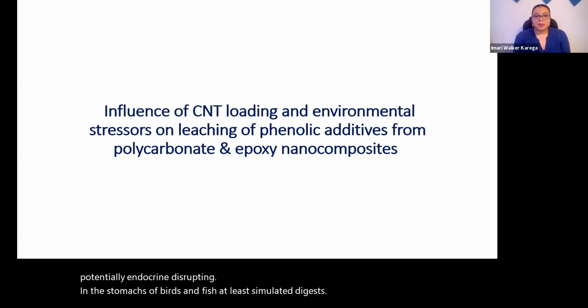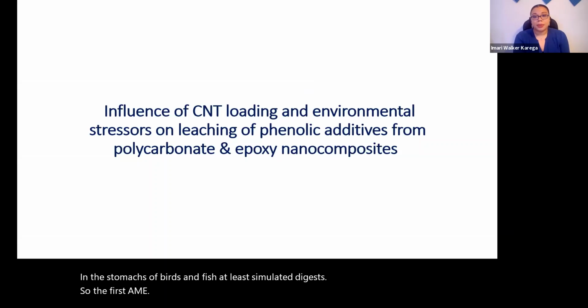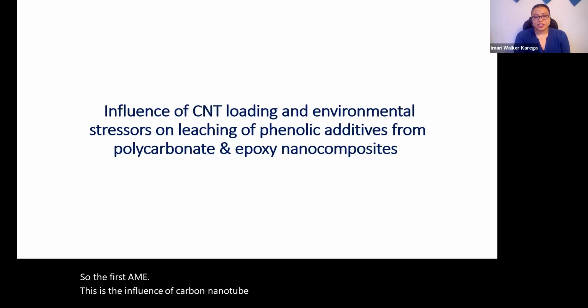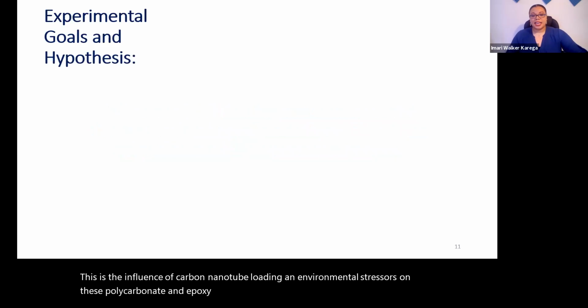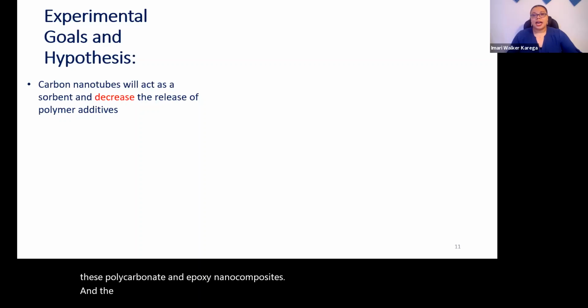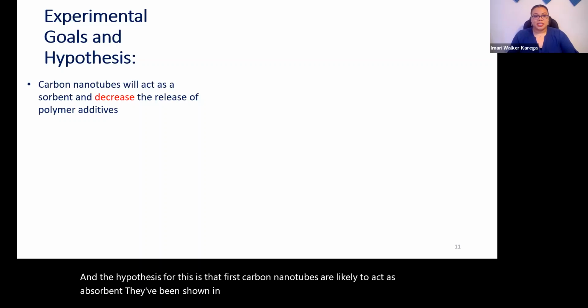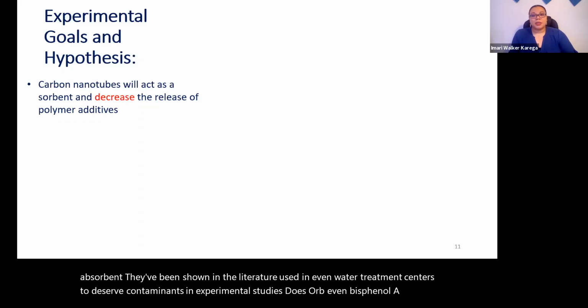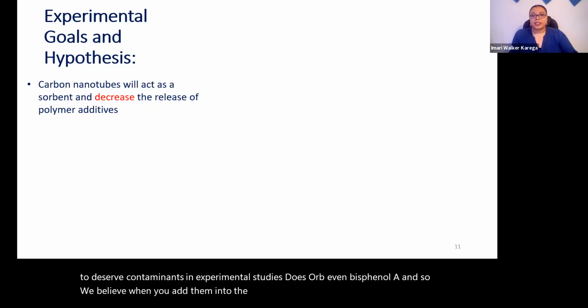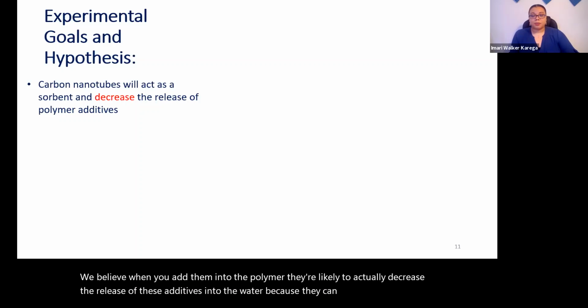The first aim examines the influence of carbon nanotube loading and environmental stressors on polycarbonate and epoxy nanocomposites. The hypothesis is that carbon nanotubes act as a sorbent—they've been shown in the literature and used in water treatment centers to absorb contaminants, including bisphenol A in experimental studies. So we believe adding them to the polymer will decrease the release of additives into water because they act as a secondary sorbent.